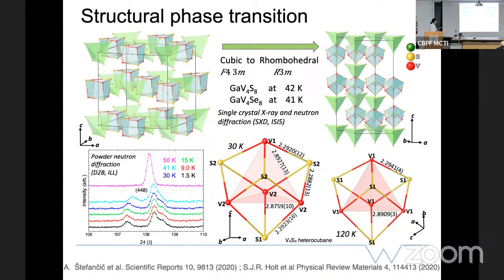And we were actually able to follow it as a function of temperature by doing powder neutron diffraction at the ILL in Grenoble in France. And we've also done single crystal X-ray and single crystal neutron diffraction using the SXD instrument at ISIS, the spallation source in the UK.